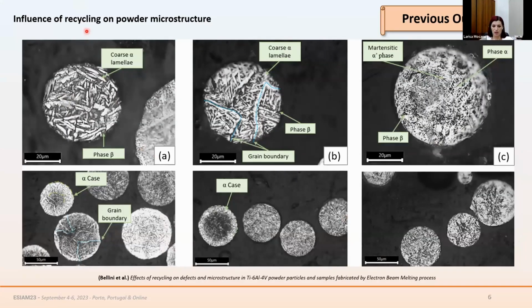Regarding the microstructure, we saw differences in the microstructure here in batch A and batch B, and this is probably due to the slower cooling rate during the production process, while regarding the virgin powder, due to the higher cooling rate during the atomization process, we have a mostly martensitic microstructure. Another interesting thing is this alpha case, which was observed only in the two recycled powders. This alpha case is a layer rich in oxygen around the particles, which is also brittle and harder than the core. But this needs to be properly investigated.